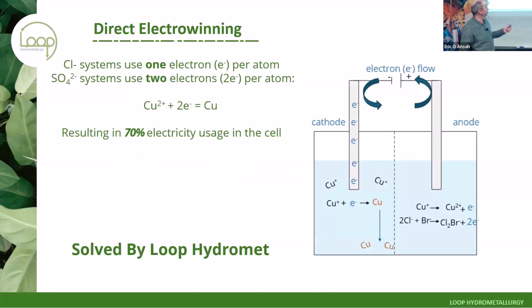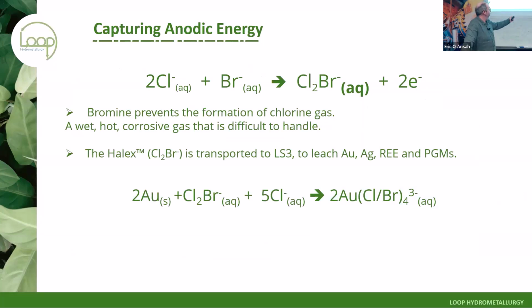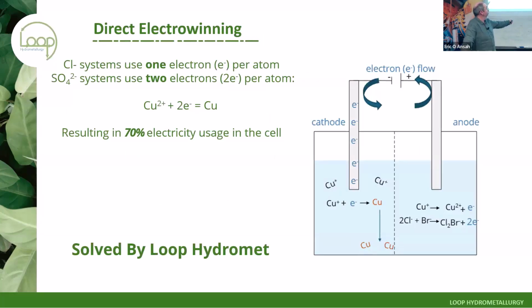Okay, so in simple terms, the Halex electrowinning cell operates off some pretty simple chemistry. You've got your copper 1 reacting with an electron to form copper metal. Nice and simple. So we feed pregnant liquor into the cathode as catholyte at about 80 grams per liter. We do a 50 gram per liter strip, so we produce approximately 50 grams per liter of metal.